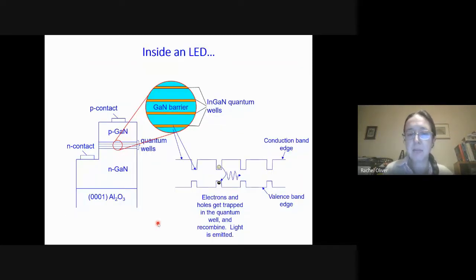Well, we were inside an LED before as a SEM image. Now I'll just draw a schematic and talk about what's happening to the carriers, the charge carriers, the electrons and holes in this material. So what we want in an LED is we have P-type gallium nitride and N-type gallium nitride, from which holes from the P-type gallium nitride, positive charges, and electrons, negative charges, are injected into this quantum well region. The quantum well region consists of thin indium gallium nitride layers sandwiched between these gallium nitride barriers, which have a wider band gap. So we have alternating regions of indium gallium nitride, which has a lower band gap, and gallium nitride, which has a higher band gap. And that makes these kind of pockets for electrons and holes to become trapped.